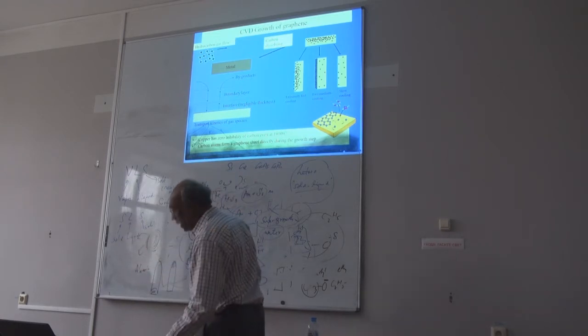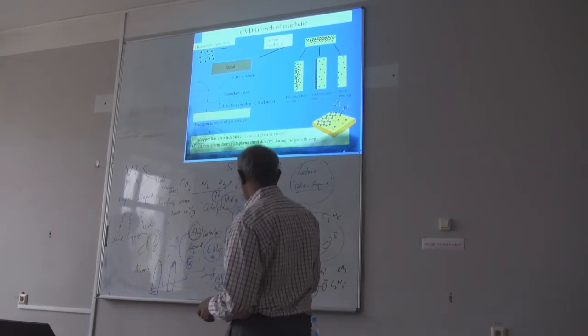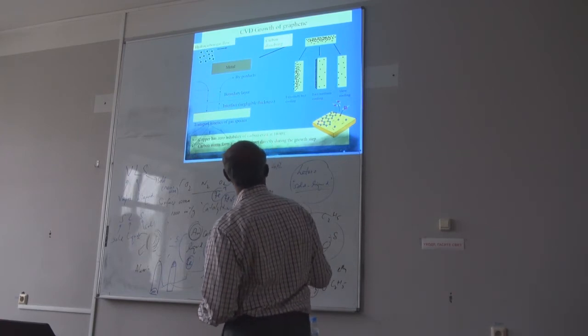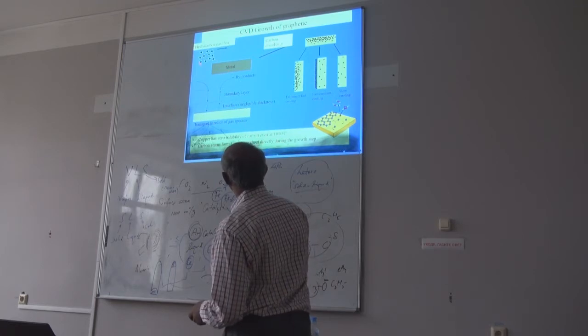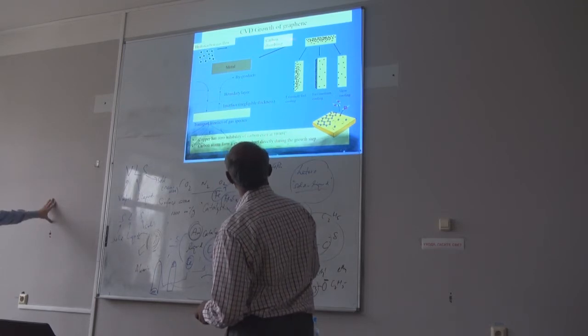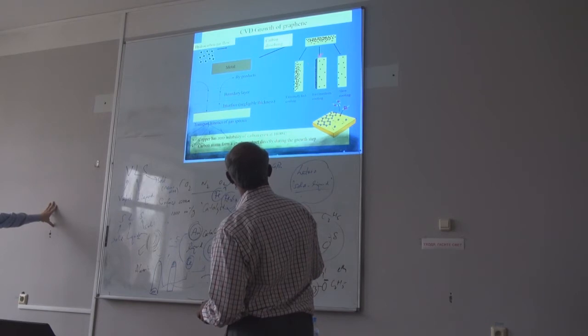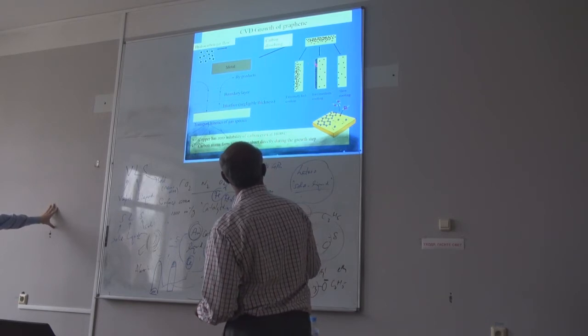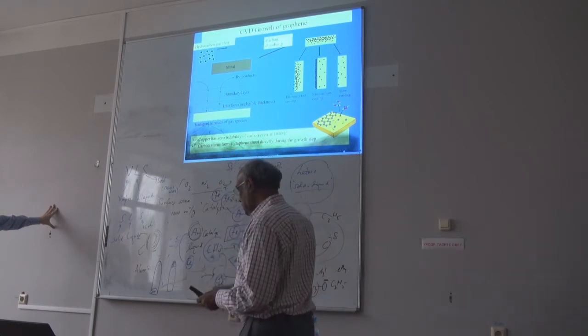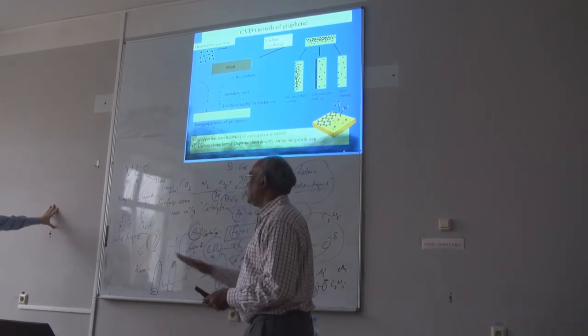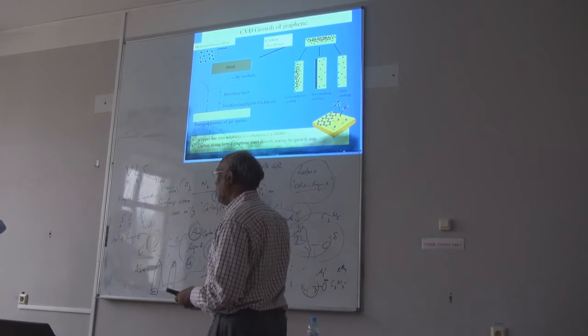So that's why people started with copper. So if you have copper substrate, when you introduce this methane gas, the carbon doesn't really mix here, so it just deposits on the surface. So then you can find graphene on the surface. So if you use copper, yes, yeah.